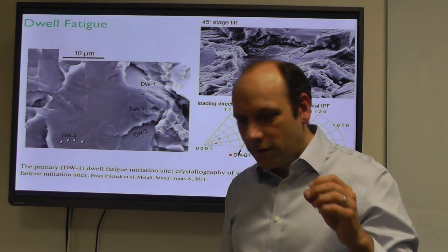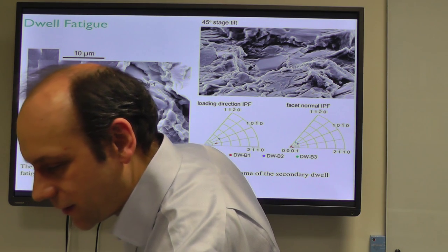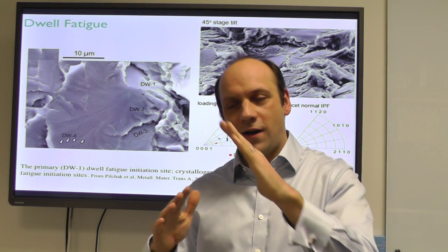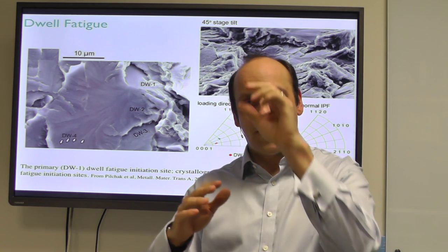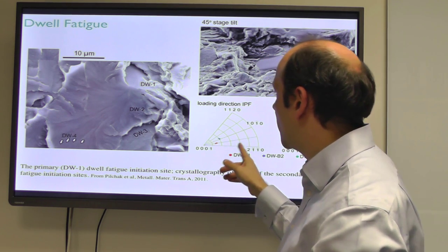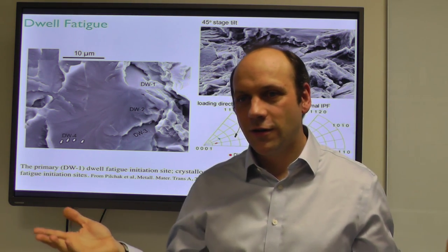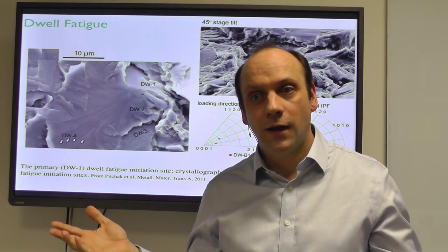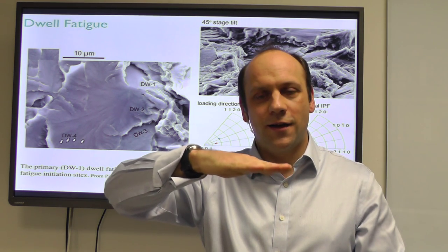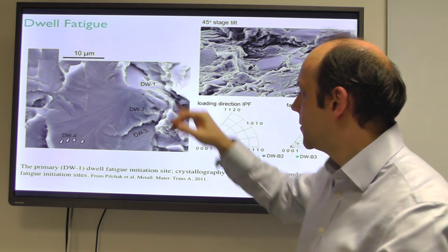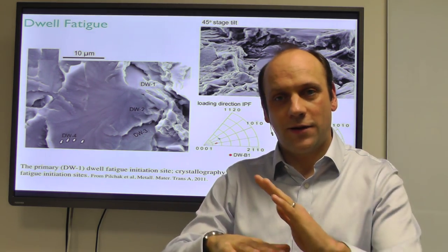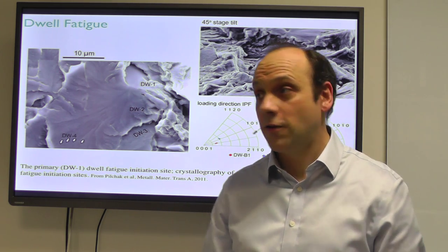So dwell is still a research topic. We're applying that Stroh model where we have a soft-oriented grain that slips back and forth, that then creates a shear band that then breaks the hard-oriented grain, that's this dwell facet, because it didn't have really very much resolved shear stress on the facet plane at all when it was loaded, because it's nearly that way, right? So its resolved shear stress is nearly none. So it must have initiated its cracking via some applied shear stress from some adjacent grain that was in a soft orientation that was